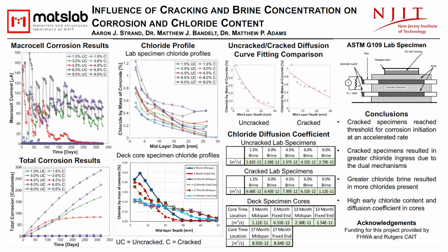The method of calculating the diffusion coefficient is based off of Fick's second law of diffusion, and due to this, when used for a cracked system, the resulting chloride content curve does not correspond to the found data. This also means that the resulting diffusion coefficients do not accurately capture the crack condition.